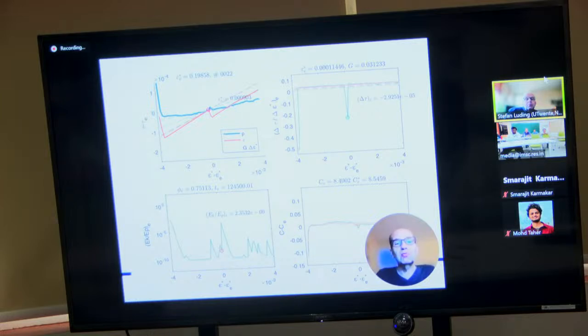This is the modulus, delta stress over delta epsilon. And the modulus doesn't change too much. There's a drop. The modulus is not active. The material has no elastic stiffness during the event. And then it goes back to almost the same level. Kinetic energy is bottom left. So here, at what we identify as the event, kinetic energy is going up, and then it's shooting up after the event even much more, and then it exponentially decays. So this is one event, kinetic energy going up by orders of magnitude and then going down again.